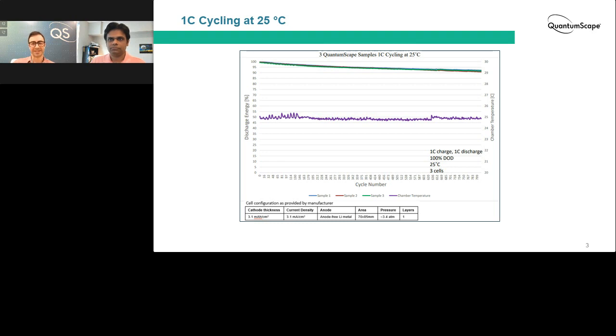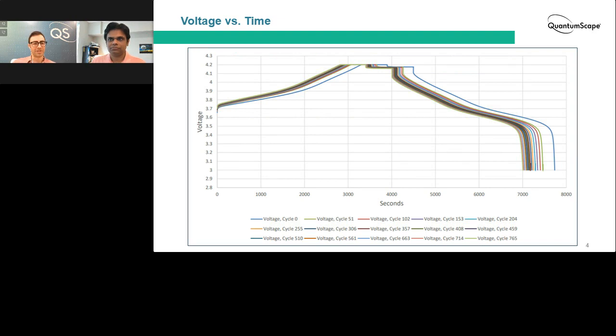Great. So let's dive a little bit deeper here. What we'll show you next is the actual voltage curves of selected cycles during this cycling test. So the blue curve that stands out a bit from the rest is the very initial charge that was done on the cells. So what you're seeing is, as the time increases on the x-axis and voltage is increasing on the y-axis, this is a charge cycle. So the battery charges from its lower cutoff voltage up to its upper cutoff voltage. It's held there for some period of time. Then there's a little bit of a rest, and then there's a discharge as the voltage decreases. So this blue curve is the first cycle that was done at the test.